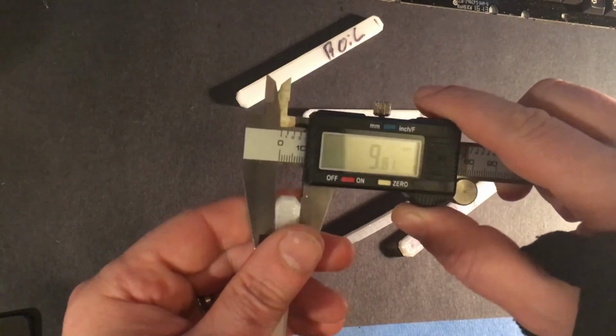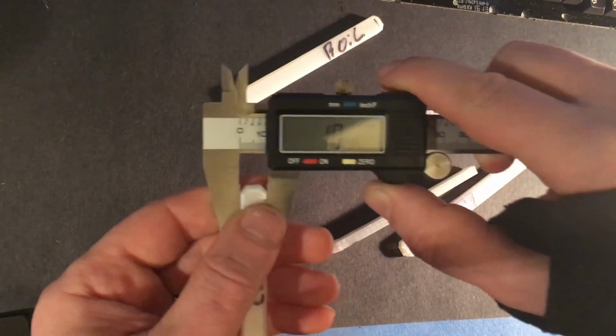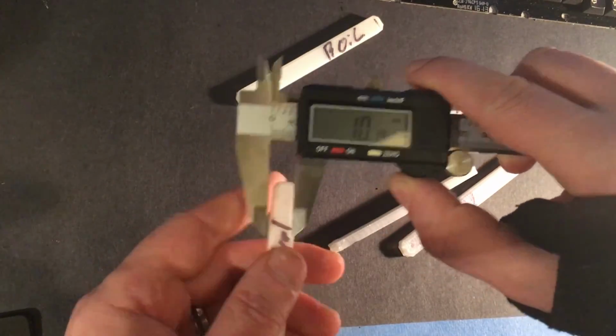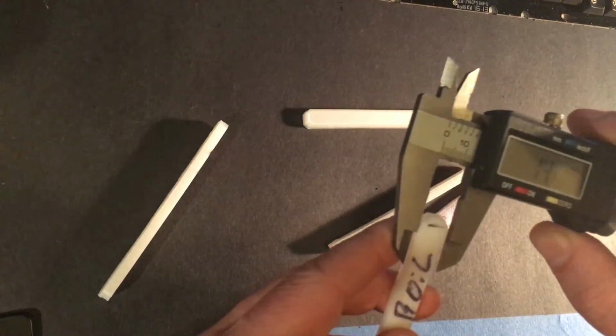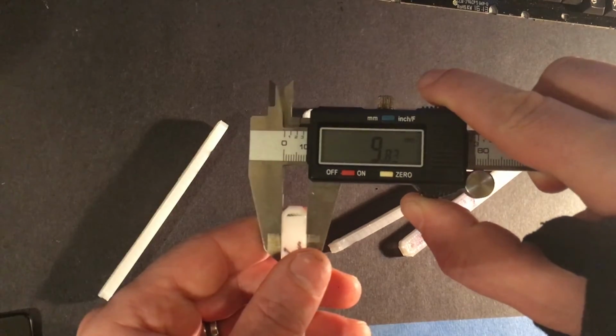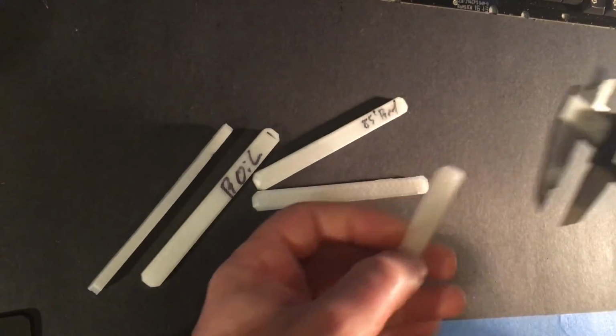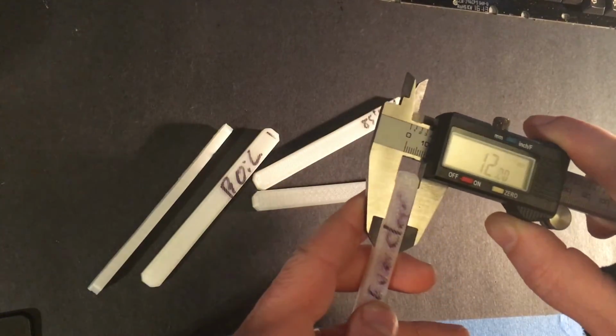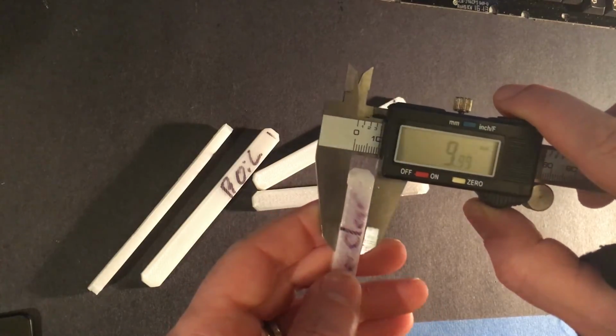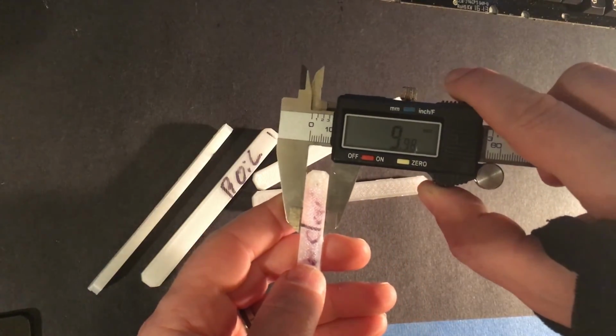Same thing goes for the width. If we look at our control sample of this supposedly 10 millimeter wide, it's a little bit over 10 millimeters. If you look at the boiled part, that's quite significantly shrunk down to about 9.8 something. And then the Everclear part is pretty darn close to the original 10 millimeters.